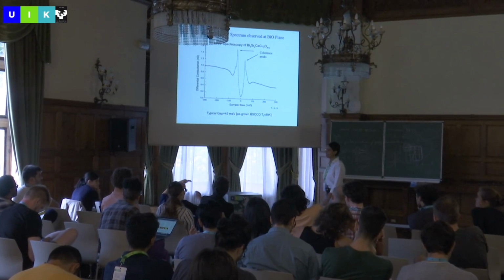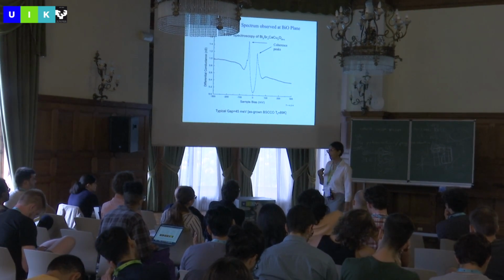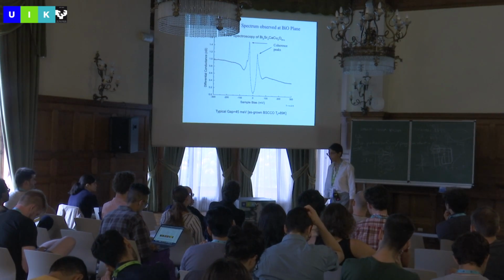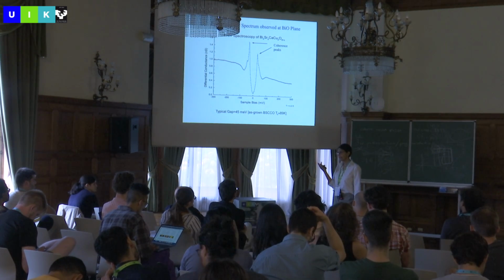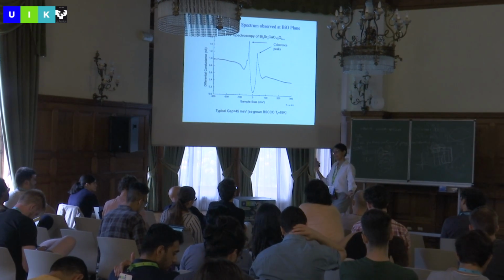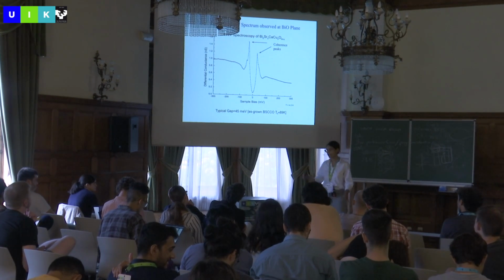So when you say it goes to 0, this is 0 to what level? And what's the ratio between the normal and the 0? Okay, so I'll tell you how we determine that. It's not a good thing to look at dI/dV. Better to look at IV. And it's the slope of the IV, right? So how flat is it, you're asking? So you compare that to the noise. So you have some noise and you have some slope, and it's much flatter than the noise usually.